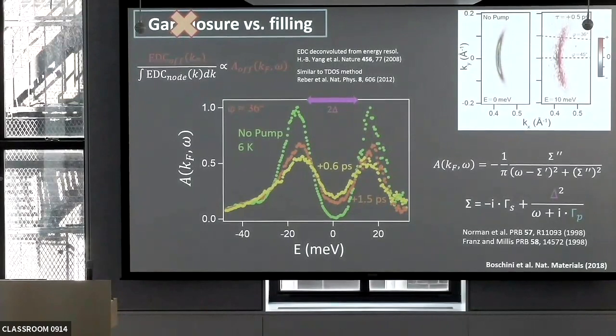Because one can interpret this slightly differently. This is antinodal, I suppose, right? Close to nodal. Well, there's a gap, so it's not nodal. It's close to nodal, it's not antinodal. But we could interpret this differently. We would say, okay, what the pump is doing is killing the superconductivity or damaging it, but we still keep a gap, as we see. So the gap is really a pseudogap, not of superconducting origin.